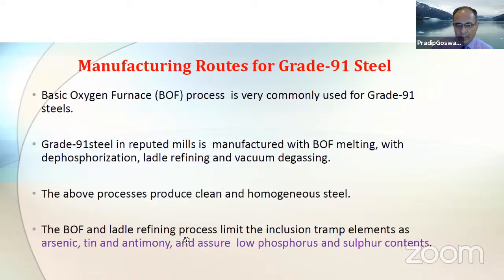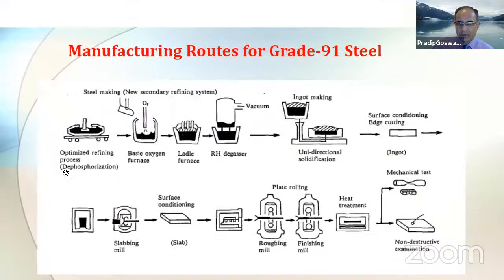The basic oxygen furnace and ladle refining limit the inclusion of tramp elements, as I mentioned earlier, like arsenic, tin, antimony, and assure low phosphorus and sulfur contents. So here is a typical manufacturing route for the steel. Starting from the steel melting process, then it goes to ladle refining, then through the degassing process, then ingot pouring. After the ingots are cast, they are shaped. Following shaping, they go into the slabbing mill where they're rolled into, say, plates.